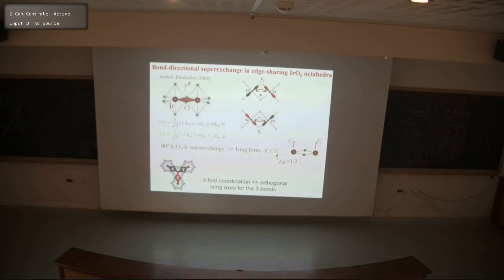So how do we generate the requirement for having a dominant Ising exchange? One scenario that was proposed by Jackeli and Khaliullin way back considers two octahedra that are edge sharing, and looks at the superexchange between the iridium, oxygen, iridium, and also going through this other path up here. In detail, this mechanism is actually quite subtle, but qualitatively, the fact that spin is strongly linked to the orbital means that there are very strong constraints as to what spin states can actually interact with one another.